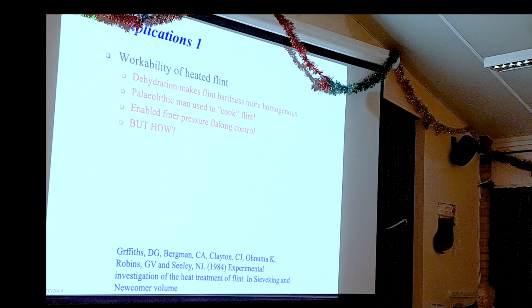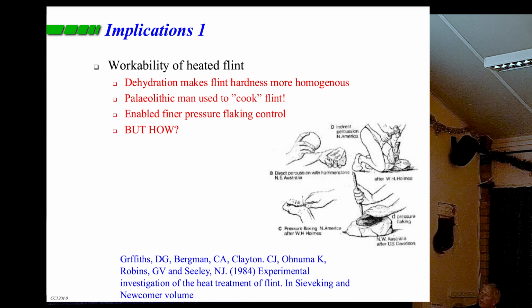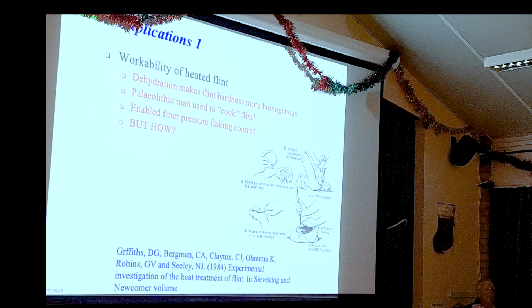So what we would do is take a sample of flint, rough it out. Then after heat treating, our archaeologists pair in here, Chris and Kiko, would actually go in and try and flake off bits. At first we gave them instructions, can you rate all these flints on a scale of 0 to 5 on how easy they are to pressure flake. They actually got back to us and said, can we use half scores? So essentially we said yes, which gave us a scale of 0 to 10 effectively of the flint.